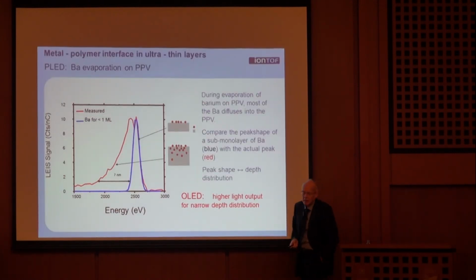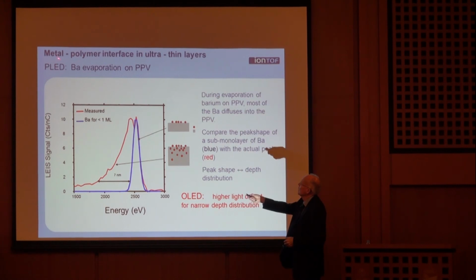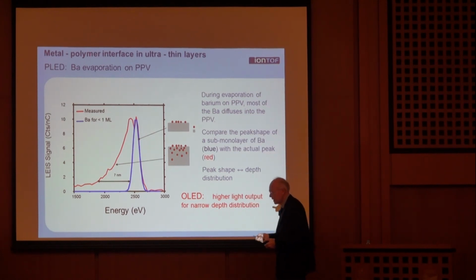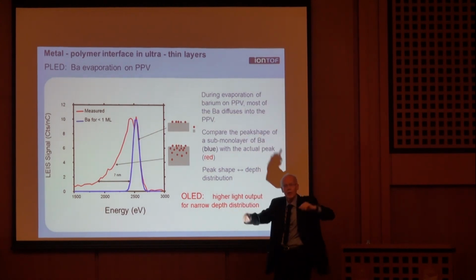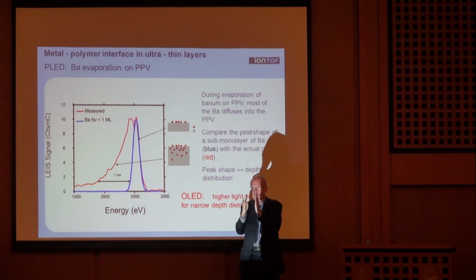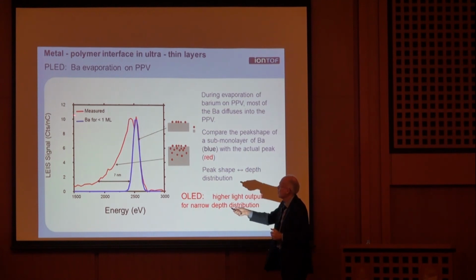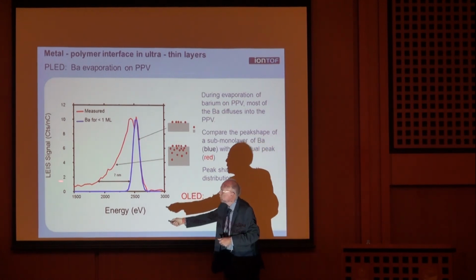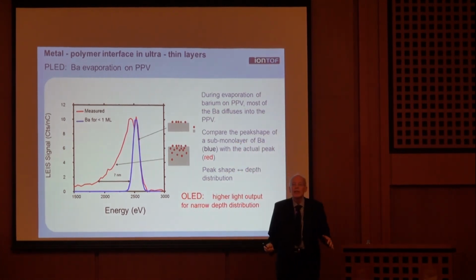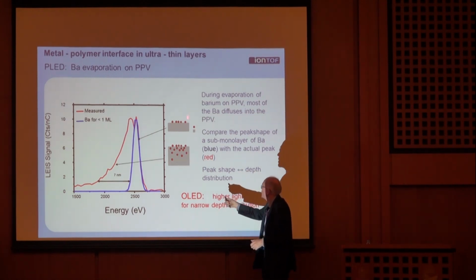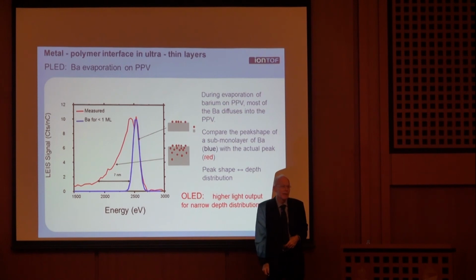For polymers, one can do a lot of work. This is a case where, to make OLEDs or PLEDs, whatever you call it, you make a metal contact on a polymer, and if it would just evaporate on top and form a monolayer, you should get a nice Gaussian peak, like the blue one, for instance for barium on a polymer. In practice, you will see the red one, it is very wide. Why? Because it's not only on top, but as you see here, it diffuses into much deeper layers.